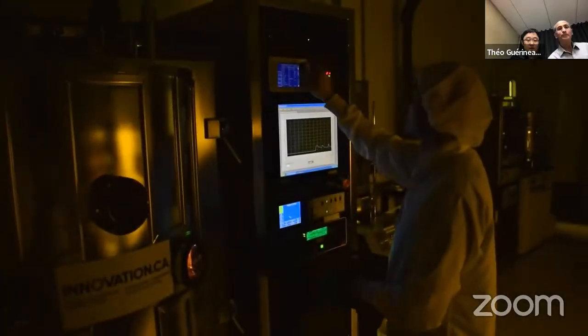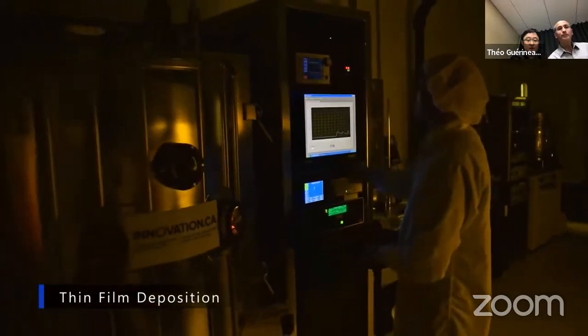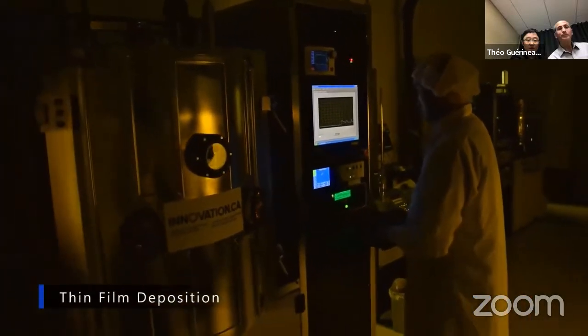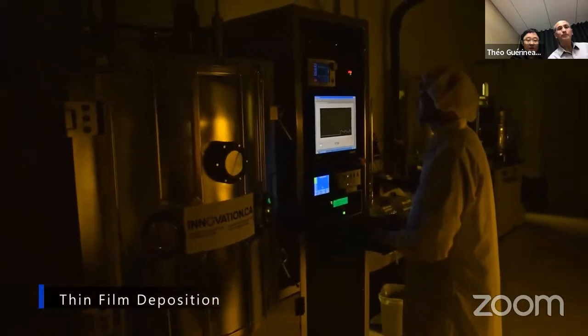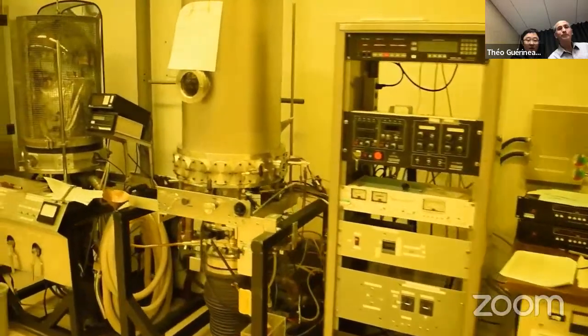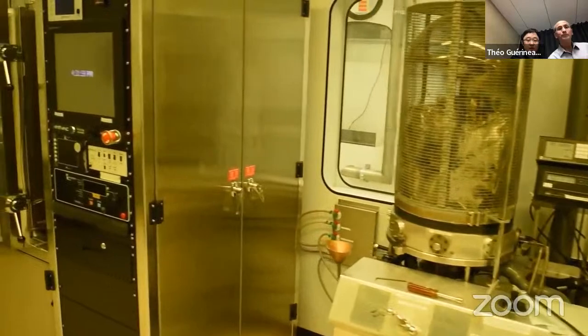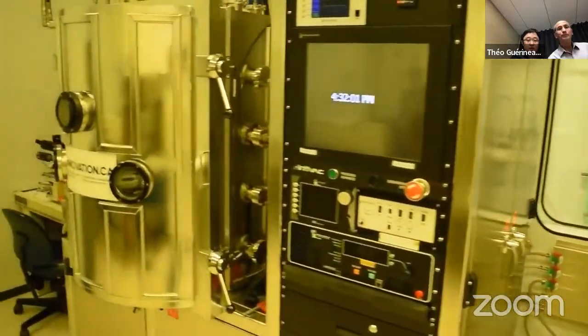The thin film deposition is performed in a hybrid evaporation system, containing an electron beam and a thermal evaporation source. Therefore, glass compositions otherwise difficult to obtain can be formed by co-evaporating materials. The wide chamber fits not only usual substrates such as glass slides and silicon wafers, but can also be used for substrates up to 60 centimeters wide, like mirrors and even preforms.